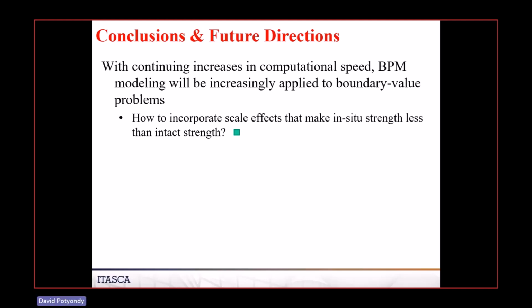My understanding is that same sort of size effect is seen in the field. Think of making the particle size smaller. There are two ways you can do this. You can keep a fixed thick-walled cylinder opening size and build materials that have smaller and smaller particles, or you can take a fixed PFC material particle size and build thick-walled cylinders that have bigger and bigger